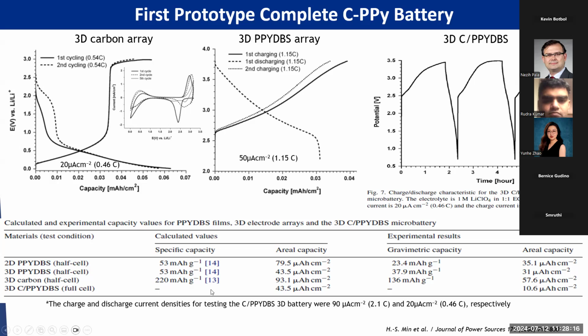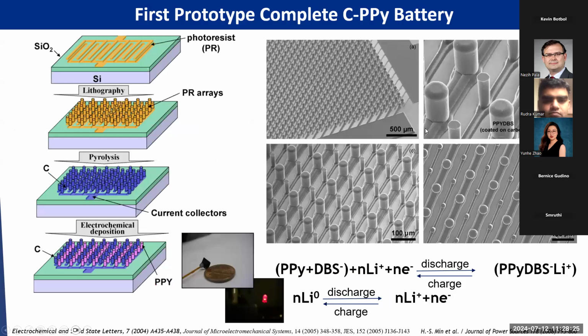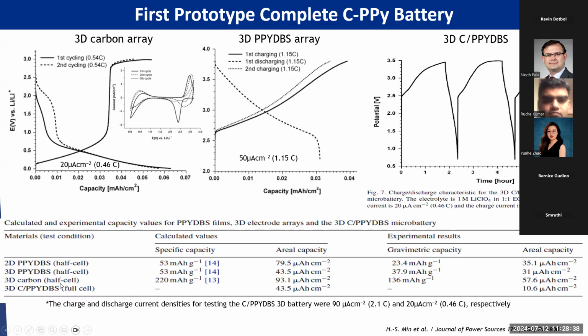You can see it at 53 milliampere hour per gram. So it's almost 4 times difference. That's why when we deposit polypyrrole, if you look at the first picture, the volume is tuned to try to match with the total capacity of the carbon. So we have to make almost 4 times higher weight. Then you look at the volume, it's almost like polypyrrole has to be doubled.